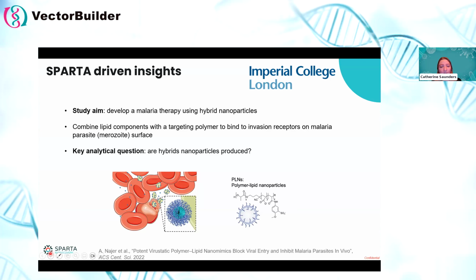So to achieve this, the researchers used a targeting polymer, which is known to bind to the receptors. However, this polymer by itself was not very effective at blocking them. It worked much better if it was incorporated into a nanoparticle. So to make sure that it was incorporated into a nanoparticle, some different lipid components were introduced. So what we end up with is you want these lipid and polymer hybrid nanoparticles to get this to really work effectively. However, this is a very novel, complex, multi-component nanoparticle. So this also then requires very careful analytics to determine how these components are spread between the particles and to understand whether truly hybrid particles are achieved.